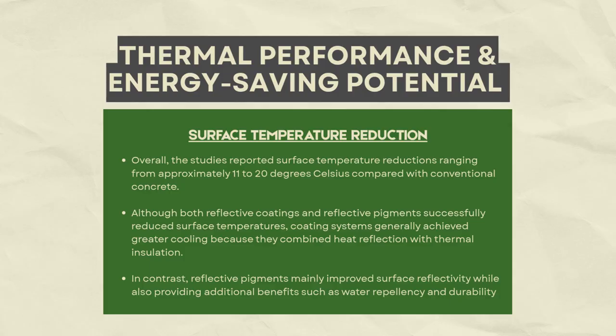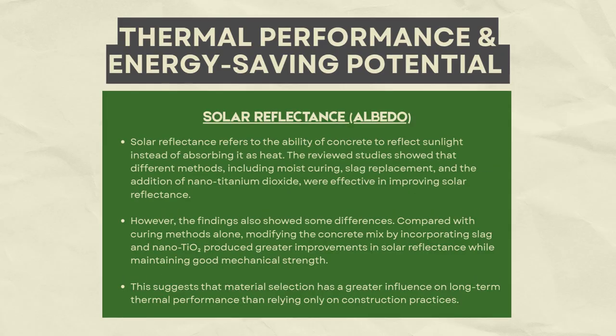Overall, the studies reported surface temperature reductions ranging from approximately 11 to 20 degrees Celsius compared with conventional concrete. Although both reflective coatings and reflective pigments successfully reduce surface temperatures, coating systems generally achieve greater cooling because they combine heat reflection with thermal insulation. In contrast, reflective pigments mainly improve surface reflectivity while also providing additional benefits such as water repellency and durability. Next is solar reflectance or albedo.